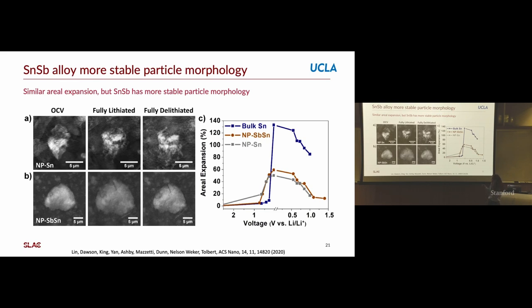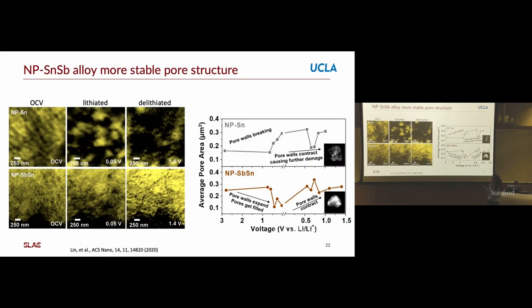So we wanted to also look and see what's happening at the nanoporous material, the nanopores. If you take a thin region near the edge of the particles, you can actually see the pores. On top is the pores for the nanoporous tin. On the bottom is the nanoporous tin antimony. You can see the pores are starting out smaller, so that might help as well. In the nanoporous tin antimony, the pores fill in when you lithiate it, and they're preserved, and they come back when you delithiate them. Whereas up top, you see the nanoporous tin. When you lithiate it, those pores just became hundreds of nanometers rather than 50 nanometers. And that got even worse when you delithiated.